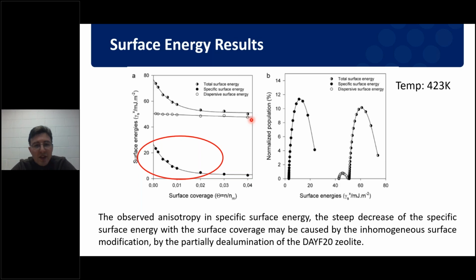We can also see a difference in its heterogeneity. It is much more homogeneous with regards to its dispersive surface energy. We can see this distribution is now much narrower when it comes to dispersive surface energy. And that is not the case with our specific surface energy. We can see it's much more heterogeneous. Its specific surface energy varies considerably depending on the concentration of the probes that I introduce.